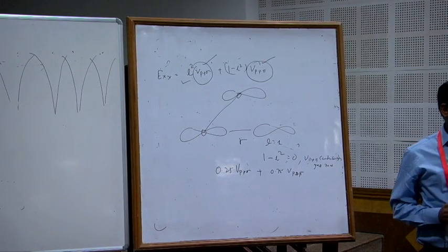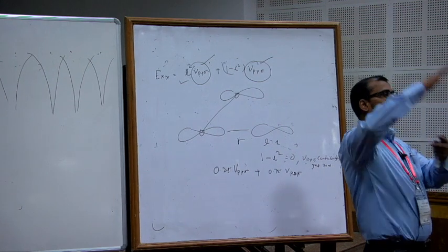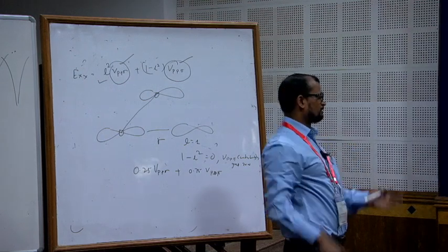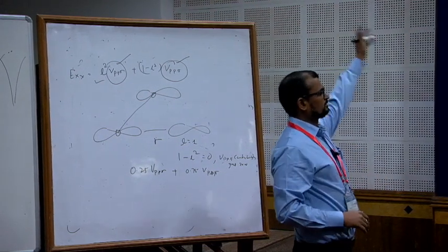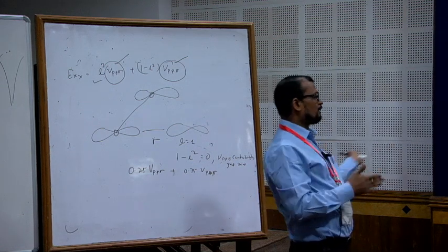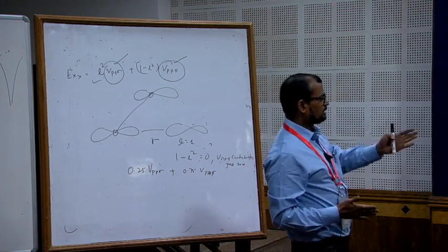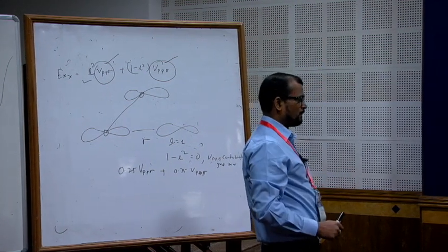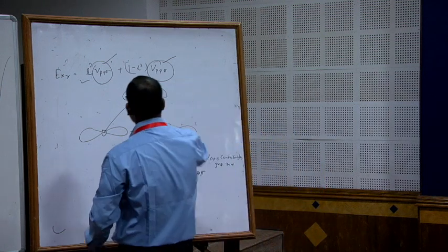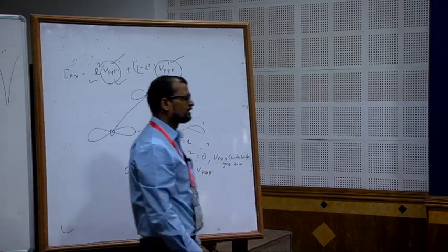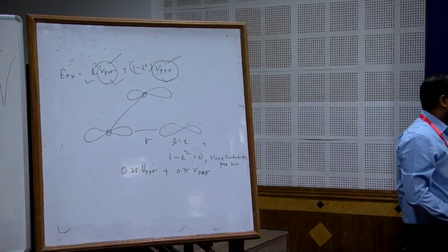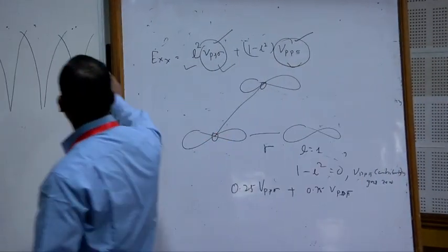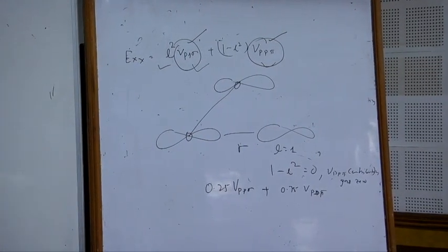What we do in this method is that we go back and look at the already available, existing all-electron band structure or certain experimental data. We fit our interaction in all these tight binding Hamiltonians to that experimental data and optimize these parameters, then give a physical picture. To explain that, we'll touch upon graphene a little bit, which I think everybody understands.